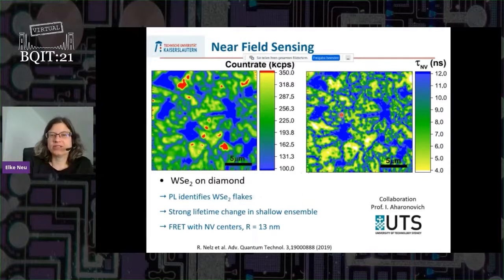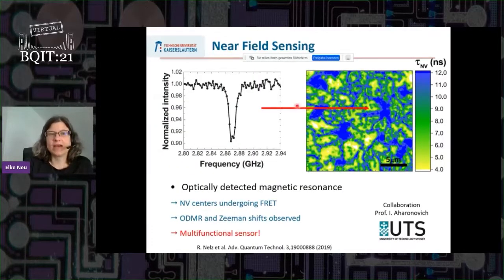And now the question is, the NV centers in these regions here, would they still work as a magnetic sensor? Would they still react to magnetic fields? And the answer is yes. We can still see this optically detected magnetic resonance if we drive the NV spin with the correct frequency. And we can also see that it still undergoes the Zeeman splitting and indeed reacts to magnetic fields.